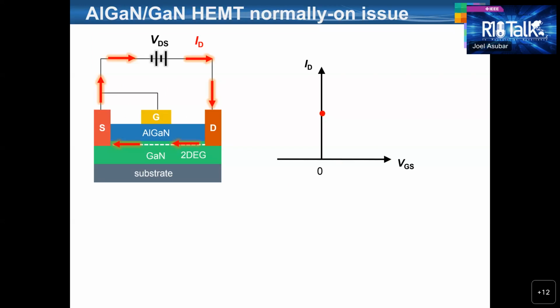In order to reduce the drain current to 0, we need to apply a negative voltage on the gate, or a negative VGS, which can deplete the 2D channel underneath, and therefore interrupt the current path, forcing ID, the drain current, to be 0 at this applied negative voltage VGS. We can connect these 2 points and add this portion of the 0 current for more negative VGS to generate this transfer curve of typical AlGaN HEMTs. This is the so-called normally on problematic issue in AlGaN HEMT power devices.